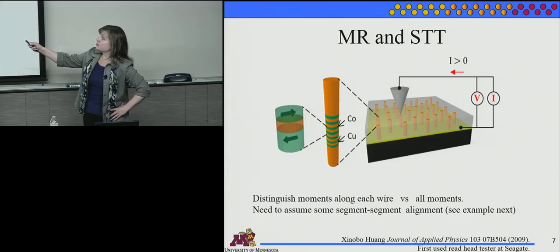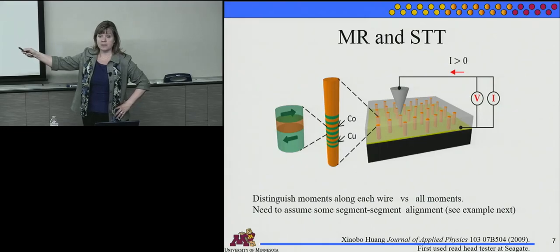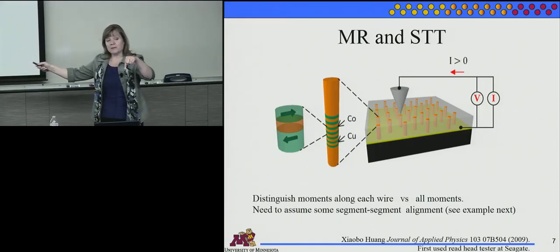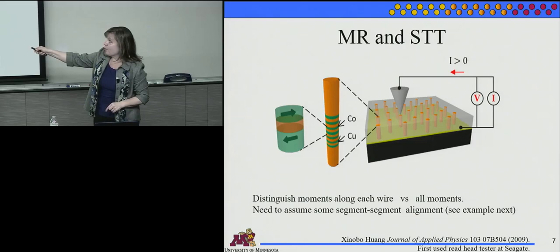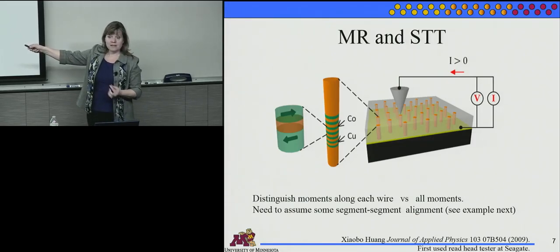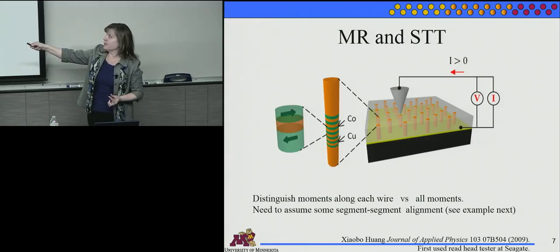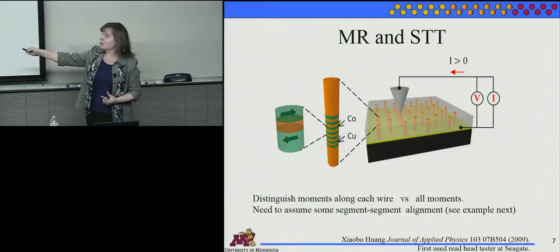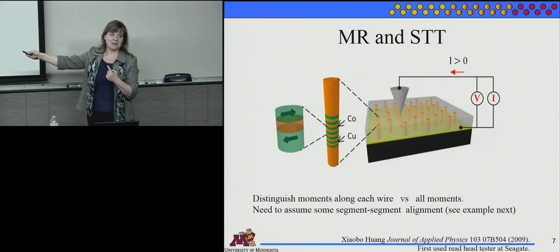Magnetoresistance and spin transfer torque switching, we're going to apply a current. This could be, for example, a gold-coated AFM tip. So you come down with a really sharp tip and try to just hit the top of one nanowire. And if it's 10 nanometers in diameter, separated from another one by 10 nanometers, it's pretty hard to find a tip that's as sharp as the schematic draws it.